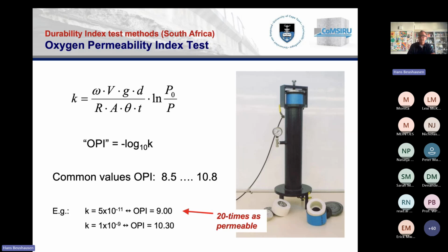Meaning, for example, if you have an OPI of 9 compared to an OPI of 10, then the concrete that has an OPI of 10 will be 10 times less permeable than the concrete with an OPI of 9. Or like in this example, typically a good quality concrete might have an OPI of 10.3, whereas a more low quality concrete might have an OPI of 9.0. In that case, the concrete with the OPI of 9.0 is around 20 times as permeable as the concrete with an OPI of 10.3.